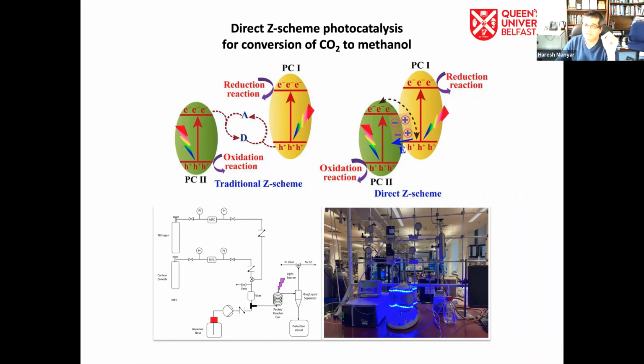So what happens here is that the electrons which were excited on the second metal oxide are far away from the holes on the first metal oxide. So we achieve enhanced separation of the charge carriers. We use two metal oxides here, an oxidation photocatalyst and a reduction photocatalyst. On one metal oxide, the oxidation photocatalyst, we have the holes, which are used for oxidation of water. On the other metal oxide, which has the electrons, they are used for reduction of CO2 to methanol. The traditional scheme is to use a combination with metals like platinum or copper oxides,